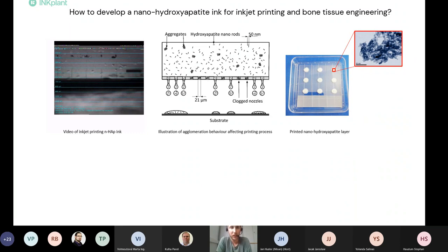The idea of using hydroxyapatite as a bioactive coating is not really new. The idea has been around since the 1980s, where research groups tried to deposit hydroxyapatite coatings on titanium implants, for example, by using airbrush or spraying methods. But by using it in an inkjet printing process, one can really control the deposition of material on the substrate, trying to print material gradients, for example. I'm really happy that we can use the nanohydroxyapatite in an inkjet printing process, because I haven't seen this before.